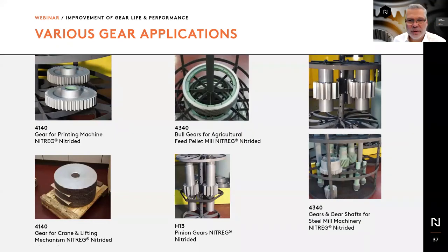Here there are several examples of gears used in industrial gearboxes. Now, nitriding is being used here for a variety of reasons. One of them is, if you look at the bull gears in the center, those gears would be completely distorted if you subjected them to carburizing. And it's also the case for larger gears, which we don't show here, for windmills and large power generation. Those gears, simply their geometry makes carburizing extremely difficult. They are also usually subject to poor lubrication in their environment because of their size. They are not entirely enclosed in a very well lubricated gearbox.